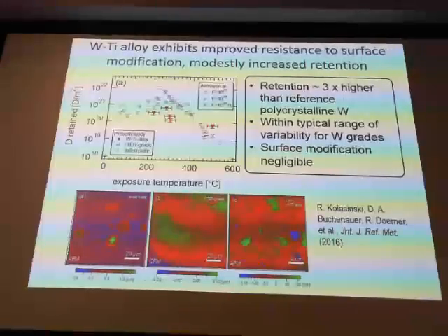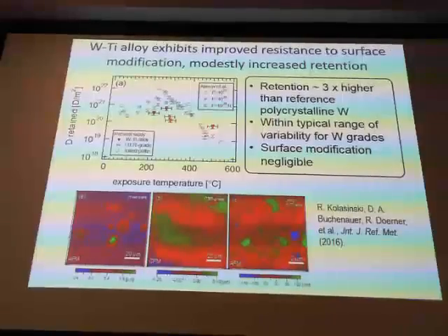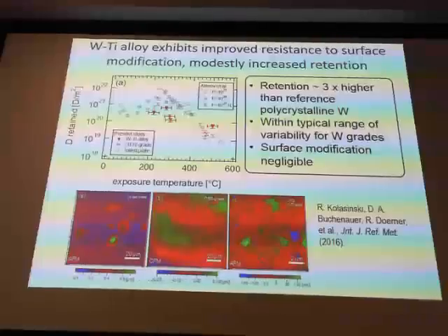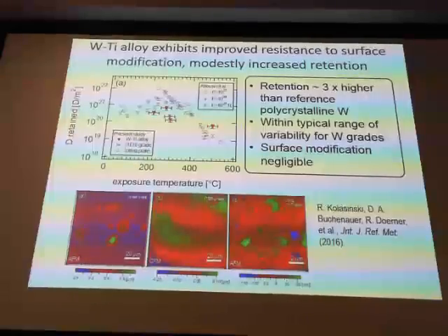So the tungsten's already quite good from a tritium retention standpoint. So we were trying to understand this, as long as the retention behavior is not adversely affected in a bad way, then this material would still be suitable. So we noticed a slight increase in the tritium retention as a result of exposure to the plasma as compared to some standard polycrystalline materials. But overall, it would probably be tolerable, and it's within the range of variability that we see for different tungsten grades. But the advantage of not having significant surface modification and the potential mechanical benefits of improved resistance to neutron irradiation would be quite a large positive for this.